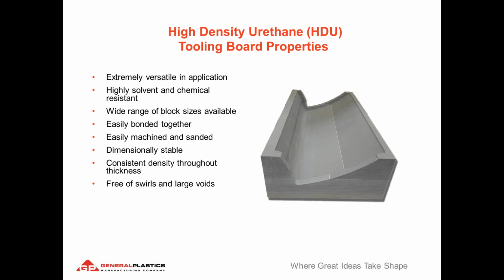Dimensional stability, also very important, talking about tooling and fixtures. When we machine out parts of foam, you don't want it to move around on you, and that's also a very important criteria to discuss with your supplier. And also consistent density throughout the thickness. We'll talk a little bit later on how important density is to properties, especially when talking about autoclave type cures, where you have external pressure on the foam as it's heated up. And also swirls and large voids can pose problems as well. Tooling boards are now manufactured really free of these types of defects. And swirls and voids, of course, just cause more handwork after your machining operation may reveal some defects.